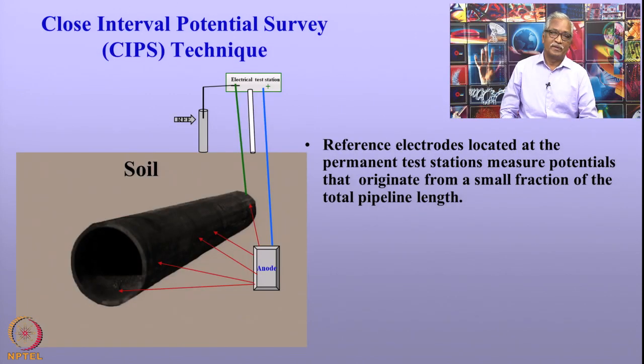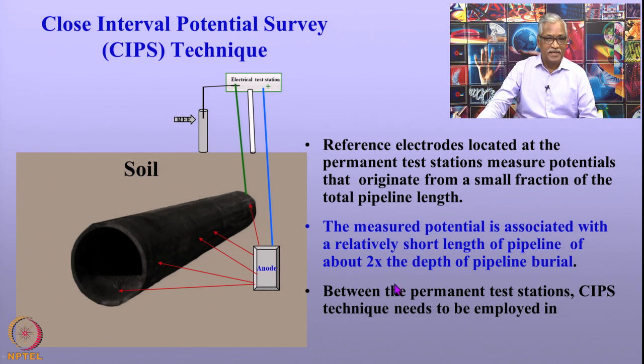Let us go into the field applications, and how the potentials are measured in the field. One type of potential measurement is called the close interval potential survey technique. This technique is used to measure the potential of the pipeline along the pipeline. Normally, in a cathodic protection system, a reference electrode is kept at the test station. The potential measured by this reference electrode corresponds to the corrosion of the pipeline in the near vicinity of the electrode. For example, it can be about twice the depth of the pipeline. If the pipeline is about 1 meter deep, the corrosion condition of the pipeline about 2 meters on either side of the reference electrode can be seen.